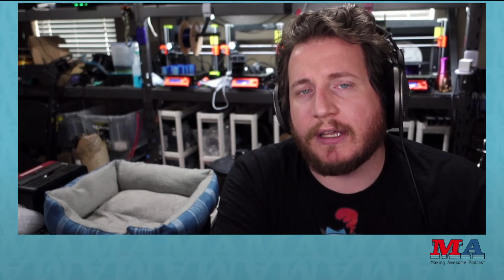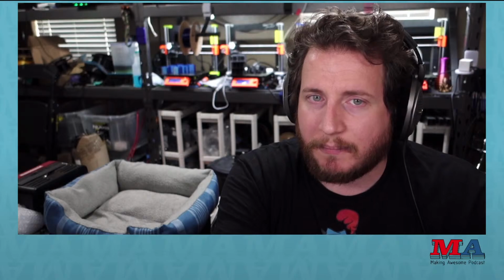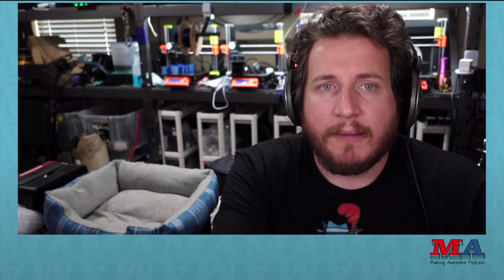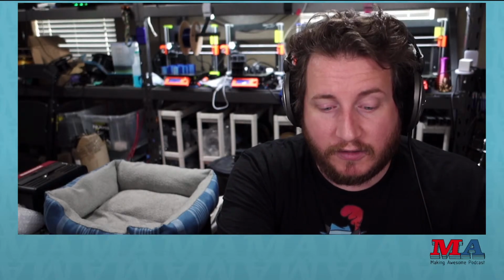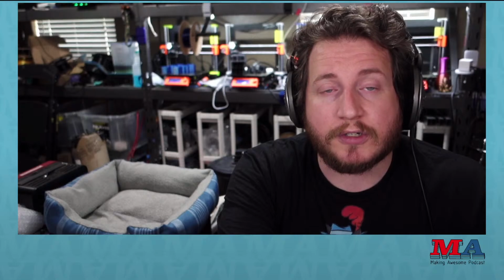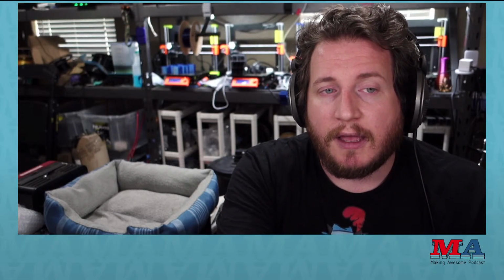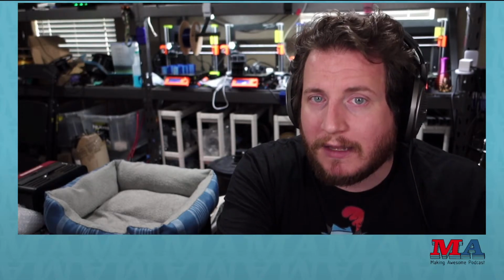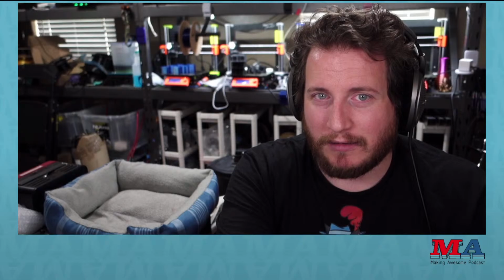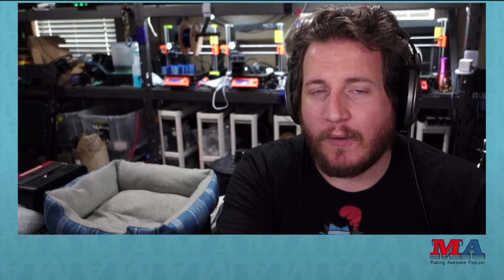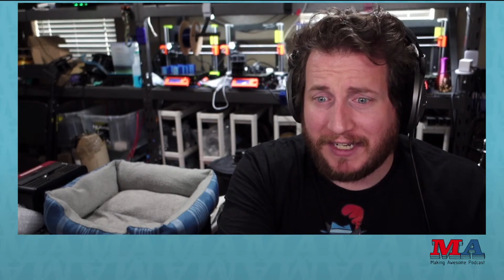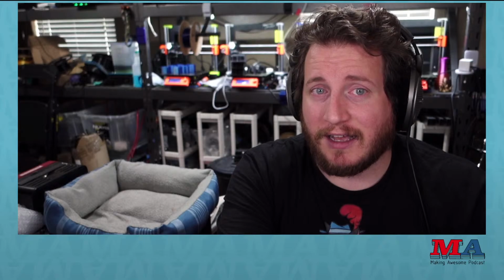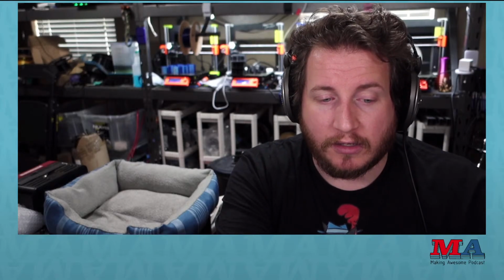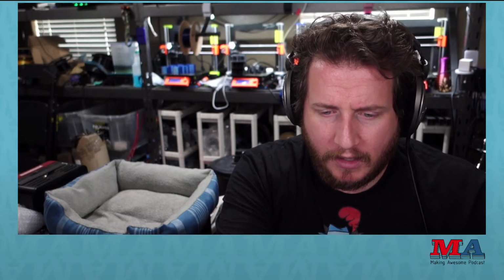I worry that people will try a PA12 nylon because, oh, it works great on SLS, which it arguably does. It works phenomenally on SLS. But as a raw filament, it doesn't work very well. You have to overheat nylon quite a bit, and drying at 70°C is a start for nylon. You gotta let it dry for a long, long time.